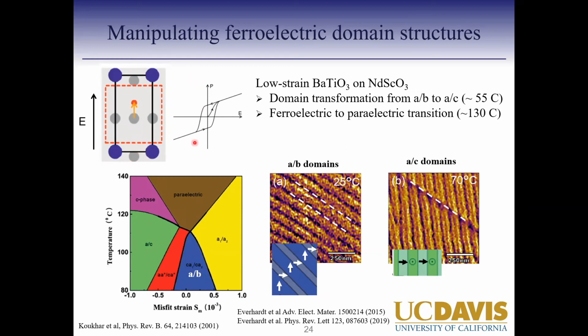Depending upon how you're growing these systems, depending upon the misfit strain of how you're growing this barium titanate thin film, you can have interesting domain configurations. So if you have very low misfit strain around here, you can have an A or AB domain structure. So it's a striped domain where you have the titanium atom shifting in the A direction, and the titanium atom shifting in the B direction. A and B refer to the crystallographic directions. So you have this AB striped manner. And as you heat it up, it can transform into a different domain structure before going back to the cubic phase.